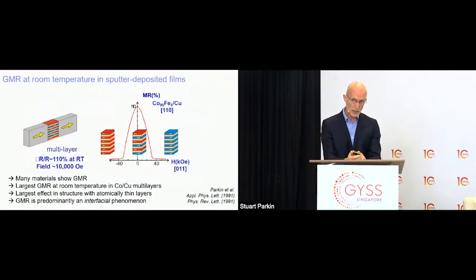Now we make a multilayer of ultra-thin, let's say, cobalt layers separated by copper layers, and we design a structure in which those magnetic moments in the superlattice are antiparallel to one another in zero magnetic field, as shown in this cartoon. When we apply a magnetic field, then we can cause the magnetic field to rotate all the magnetic moments in the superlattice so they become parallel to one another, and this leads to a drop in resistance.